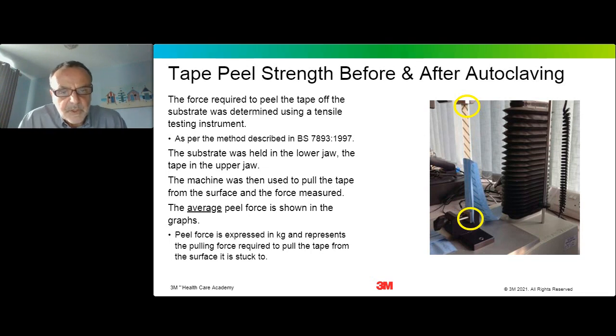So this is the method which would be used typically to determine the force required to peel a tape from a surface. So this adhesive strength was tested using an instrument called a tensile testing apparatus, and you can see it in the right-hand picture. So in this device, a tab of tape was secured in the upper jaw of the instrument. You can see that highlighted by the yellow circle in the top of the picture there. The bottom part of the wrapping material was secured in the lower jaw of the apparatus, and again you can see that located in the bottom of the picture, identified by the yellow circle.